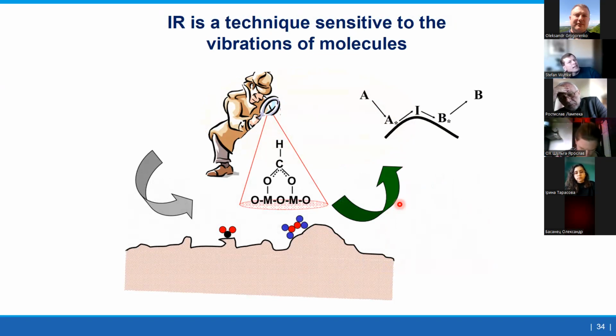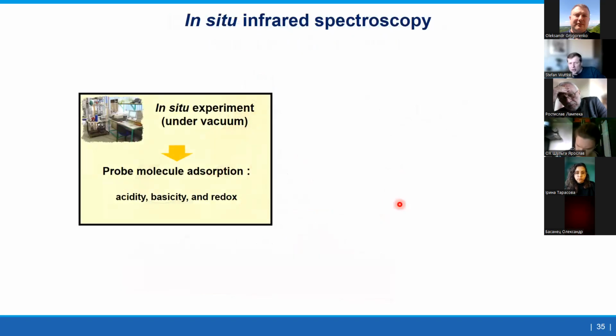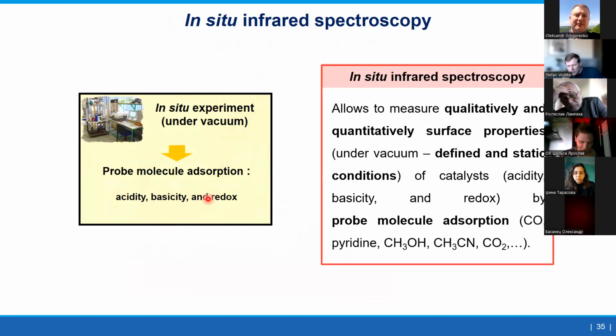And the question is how we can use these vibration modes to understand our material, our heterogeneous catalysis. And there's one important technique, it's called in situ infrared spectroscopy. In situ means under vacuum. So you put your material under a condition that you control, and then you take probe molecules. I will tell you in a moment what these probe molecules are, to study acidity, basicity, or redox properties of the catalyst. So in situ can measure qualitative and quantitative.